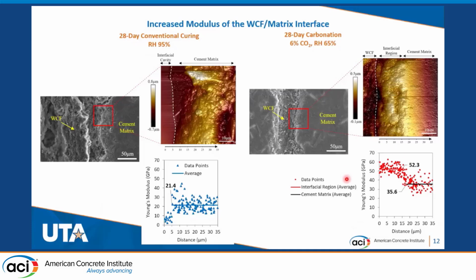On the other hand, we see here the AFM pictures and the modulus results of the carbonated specimens. We see that the carbonated specimens present three distinct phases. The interfacial area here extends from 0 to 17 microns, and we observe that the modulus of elasticity of the interface is much higher than the modulus of the carbonated CSH. The modulus of elasticity of the interface is around 52 gigapascal, while the modulus of elasticity of the carbonated CSH is around 35 gigapascal.